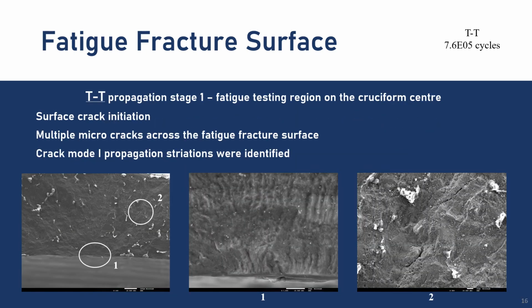Now, for TT propagation stage 1, we see surface crack initiation in the small cross-section area, showing striations associated with crack mode 1 propagation, and also microcracks across the entirety of the fatigue fracture surface on stage 1.